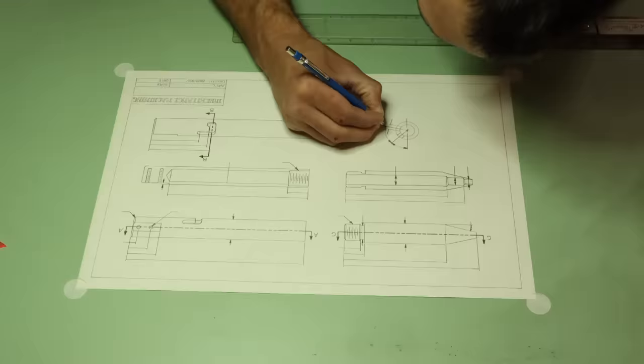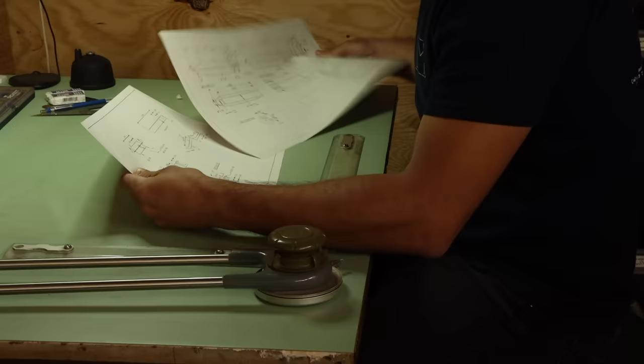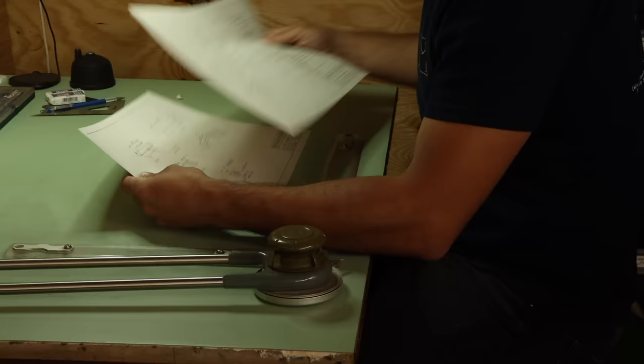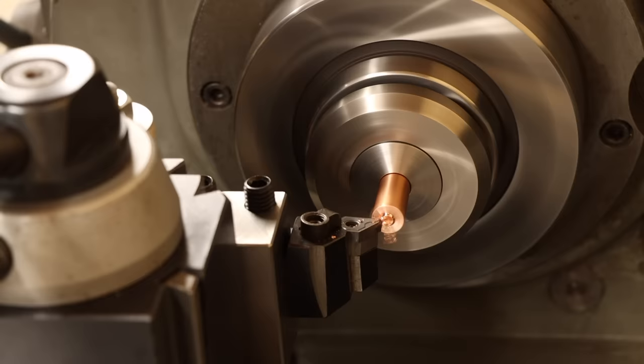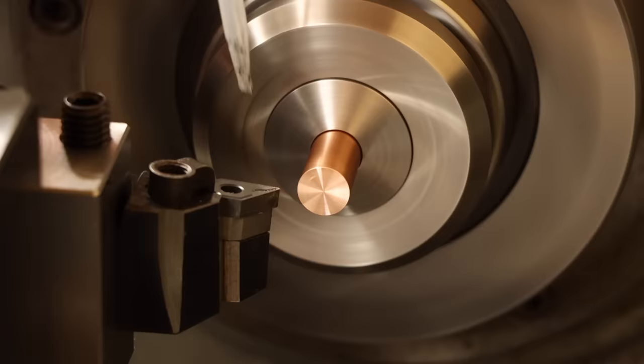With a good reliable set of drawings cleaned up and dimensioned, it's time to get to machining. Because there are several interlocking features to this design where the fits will be important, I'll have to make these parts in a specific order, starting with the barrel. Mounting the copper stock in the collet chuck, I'll first face the end clean. Except that looks like dog shit. Off to a great start already. The copper is super gummy and it likes to stick to the tooling, but just a little bit of oil on the cutting tip makes a night and day difference.